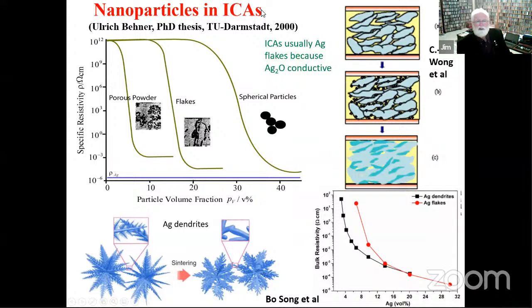So for isotropic conductive adhesives, typically the metal is silver, which is used because silver flakes, if they oxidize, are still conductive. That's because the oxide is a degenerate semiconductor. Unlike copper, which would be better, except that the copper oxide is an insulator. So we get lower resistance going from spherical particles to flakes, because a flake has a larger surface to volume ratio, so you get lower resistance for the same amount of silver.